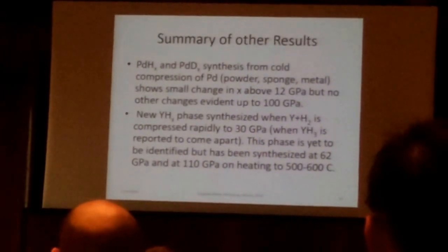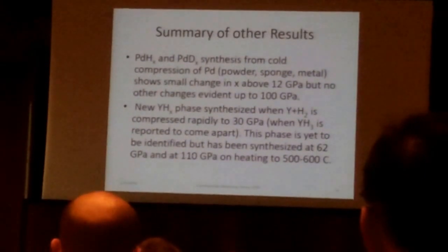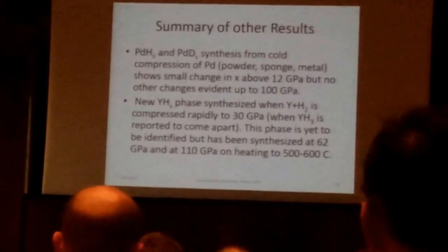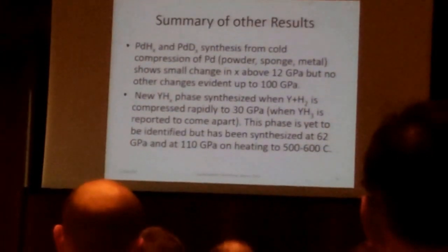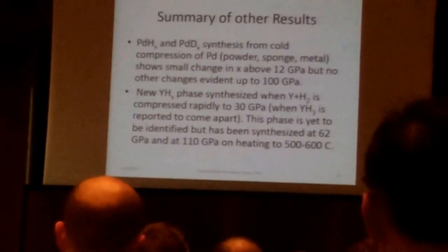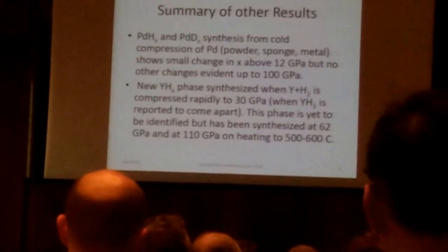And you have to load them in a glove box with very low oxygen and hydrogen content. And secondly, the form of the material you are using seems to dictate the kind of interactions you are having, because once the interaction occurs on the surface, there is not much diffusion happening at high pressures. And the reason we are using high temperature is probably dictated by the fact that the diffusion constants are low in these materials.